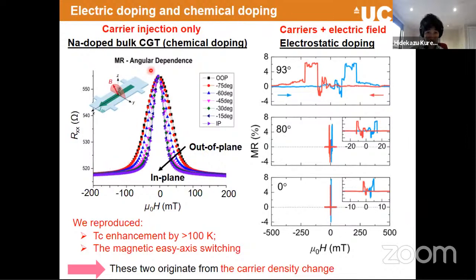While in the bulk doped regime the switching is smooth, if you look at the thin film regime, the switching is very, very jumpy. So clearly that is affected by this domain wall switching mechanism and other things. And that's the interesting point to make. The other thing I want to mention is that the size of the magnetoresistance is the same for the bulk regime.